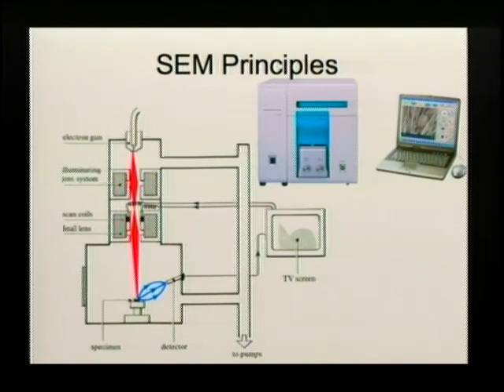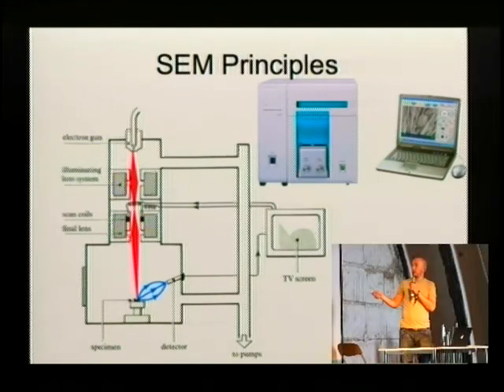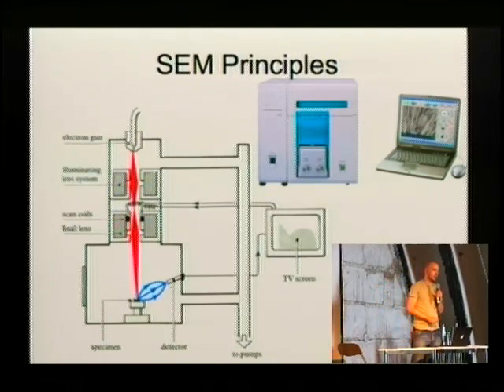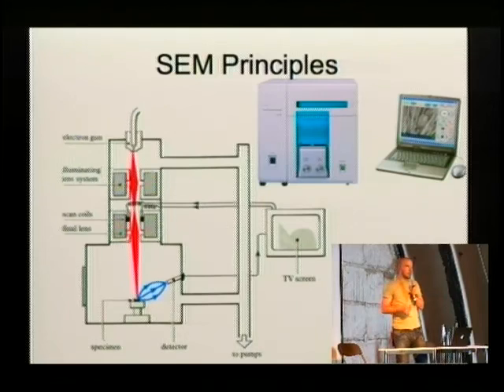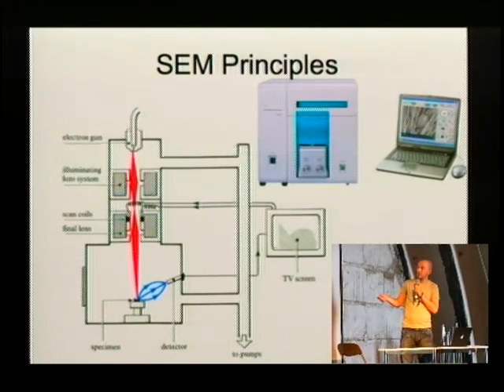Like in a light microscope, you have a lens system that transforms and focuses the beam that you get from the gun. The difference between a scanning electron microscope and a light microscope is that you create a very tiny beam that is focused on the sample, and then you use scanning coils to move the beam around on the surface, to scan the surface. While you scan, you collect the electrons that come out of the sample with a small detector in the chamber close to the sample.